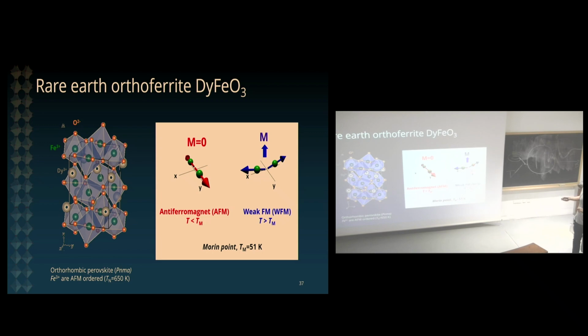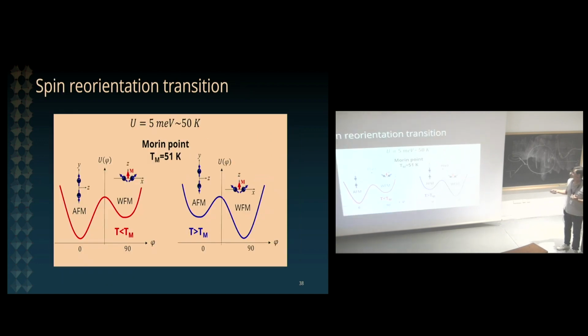You have a collinear state along a specific axis, and just above 51 Kelvin, the system reorders to a state that is called a weakly ferromagnetic state, in which the spins rotate, so they reorient from the y-axis towards the x-axis, and they acquire a canting through a Dzyaloshinskii-Moriya type of interaction. So we start from a state at low temperature that has zero net magnetization to a state at higher temperature that has a net magnetization. This phase transition is of the first order. So it's characterized in configuration space by the competition of two minima that is reversed as a function of temperature. You go from this collinear state to this non-collinear state, and the barrier between these two states is of the order of a few millielectron volts.